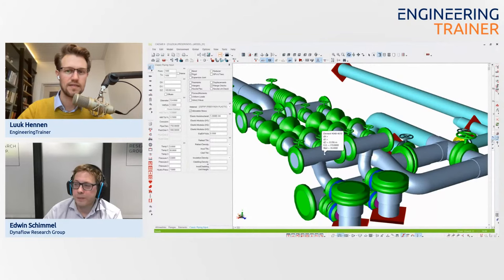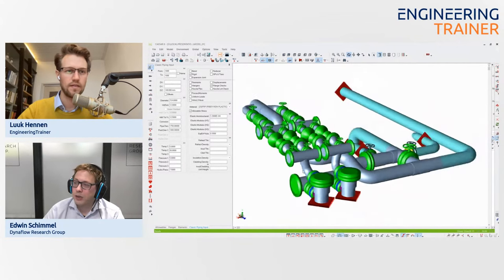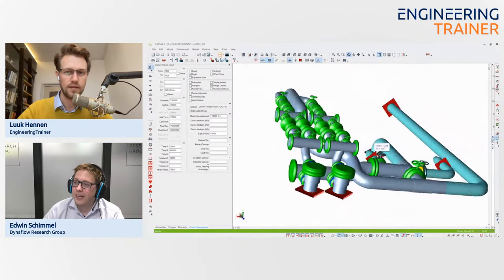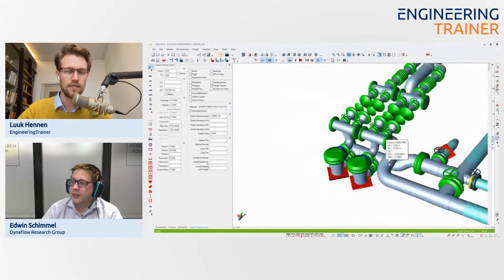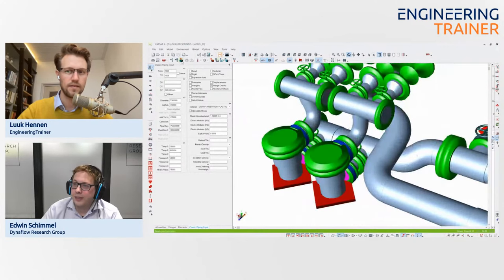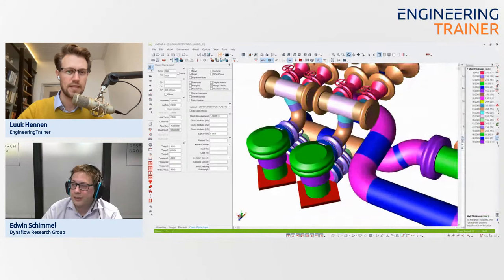So with steel, fittings are the weakest point, and then you can replace them with a different, stronger type of fitting. For example, the T, you replace it with a stronger T with a reinforcing pad. But with fiberglass, normally the highest stresses you find next to the fitting. So if we use colors to see the wall thicknesses, you see that. Oh, wow, yeah. It's very colorful now.